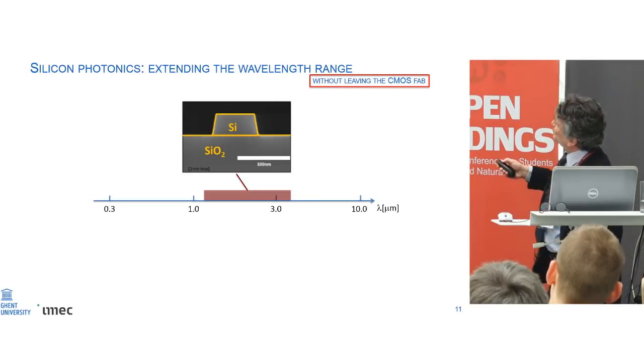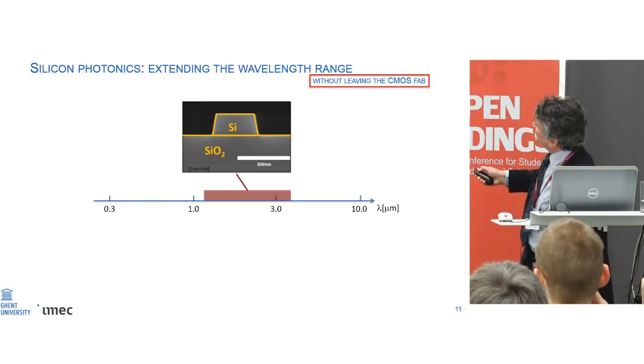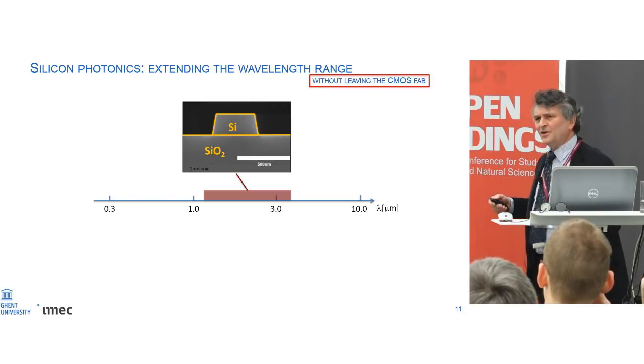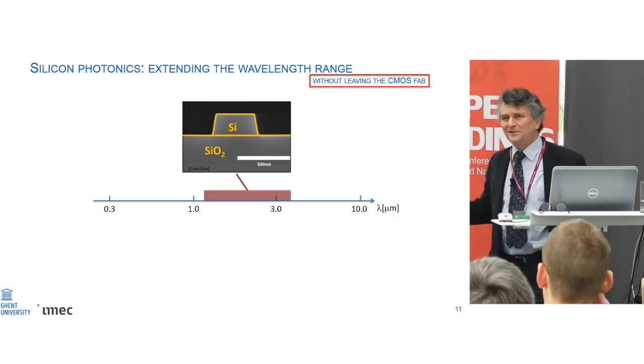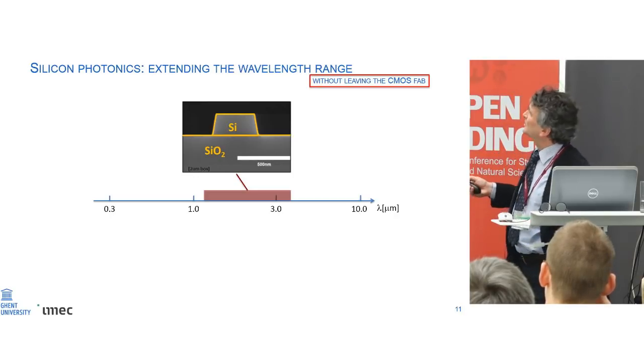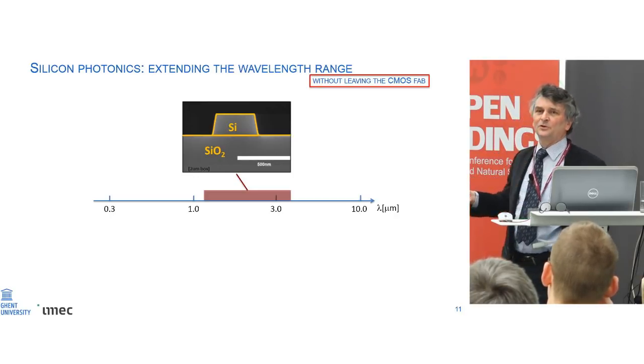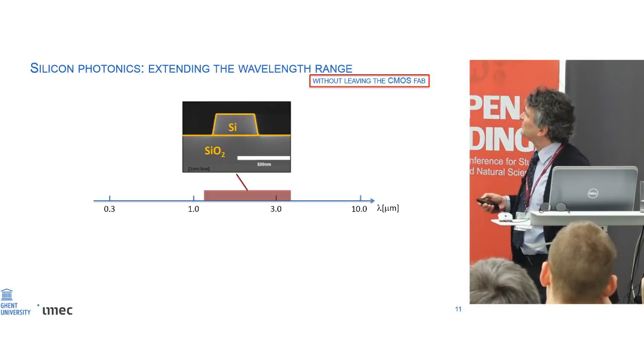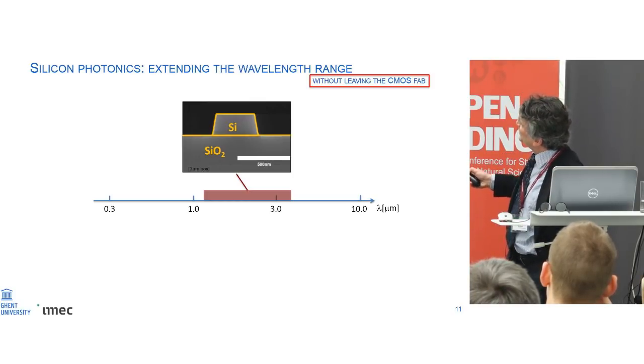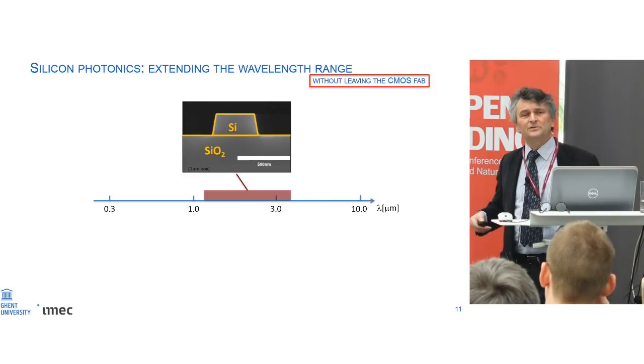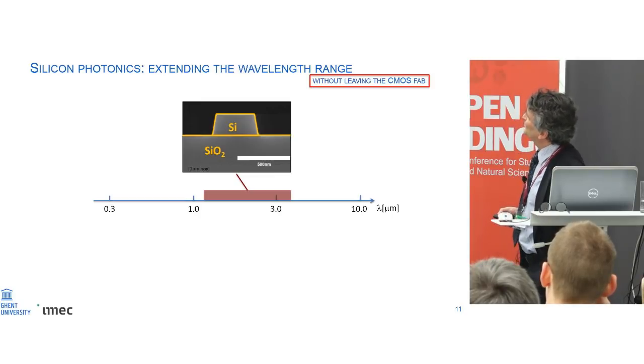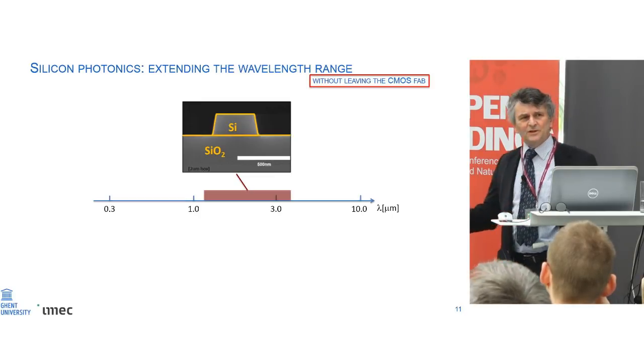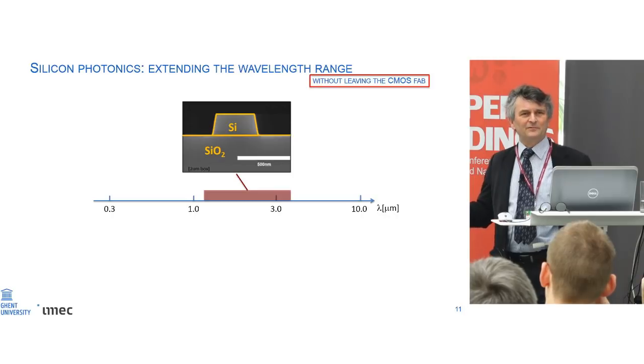So I just said we make these waveguides of silicon on silica. Now, that works well across a certain wavelength range. Silicon being a semiconductor, you can obviously not go below the band gap where silicon is heavily absorbing. And actually, the transparency window of this waveguide is somewhere from just above 1 micron. This is where the band gap of silicon sits, all the way up to something like 4 micron. That's where silicon oxide starts to be absorbing. Now, in certain applications, you would want to work in other wavelength ranges.